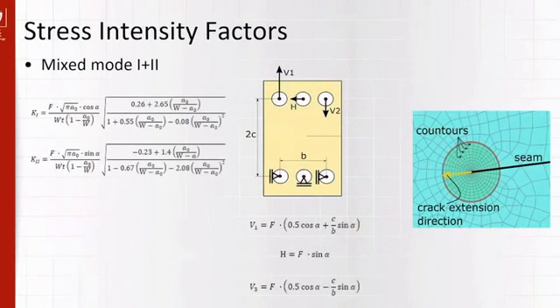In order to receive charts based on the SIF, the stress intensity factor, we conducted modeling, and in the middle of this slide, you have the model of the geometrical features of the CTS sample, and how it was boundary conditioned in Abaqus, which we used for modeling. Below the sample, you can see the formulas that represent the actual force distribution in the sample during the test.